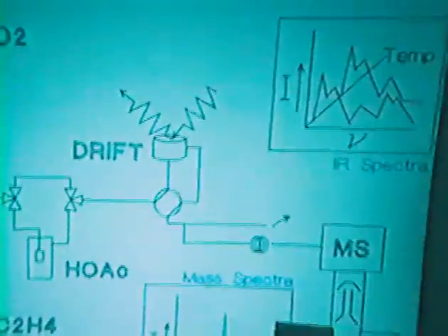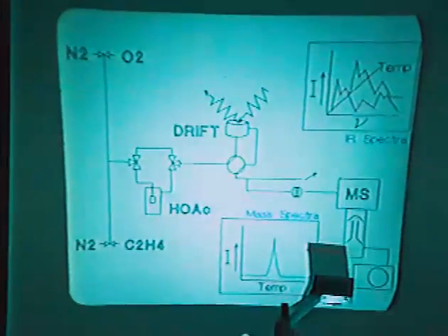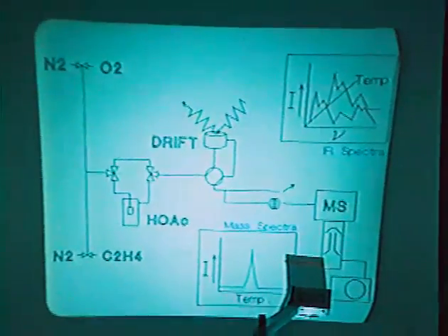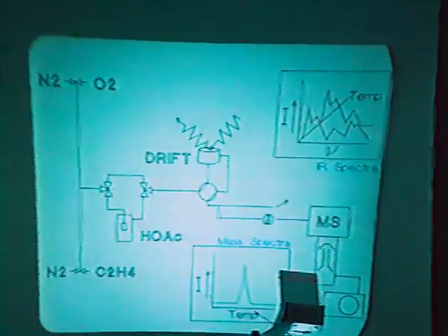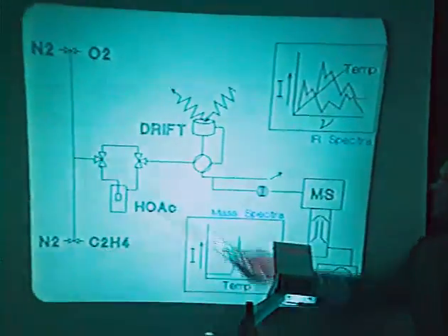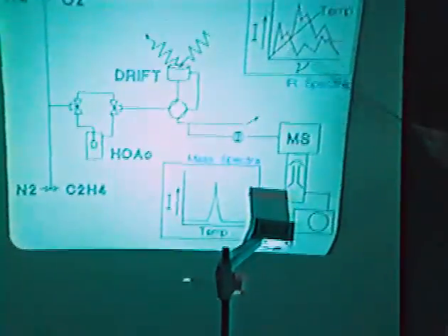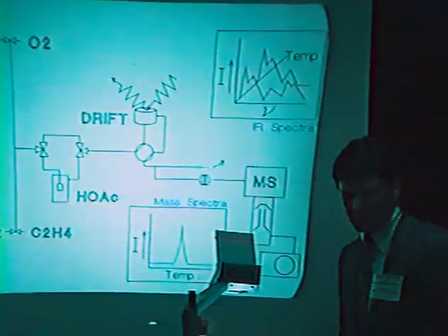And so basically, to describe how we run the experiments, we pre-treat our catalyst under steady state conditions, then sequentially take out first ethylene, then oxygen and acetic acid. Then we do a temperature programmed reaction in which we ramp the temperature, but we react ethylene and oxygen with that surface. We get off our product, and as we ramp the temperature, we see the spectrum change. I'll give you an idea of what we're looking at on the surface.